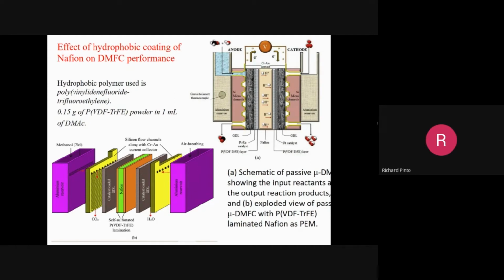The similar thing happens on the right side also. The only difference is the catalyst is only platinum, not platinum-ruthenium, because here H plus has to combine with oxygen, air-breathing oxygen, to produce water. This is the water symbol. This is carbon dioxide. So this is the current flowing in the external circuit, as I mentioned with the cross-strip geometry earlier. Electrons move in the external circuit, go into the cathode side and then combine with H plus and oxygen. So the current is drawn in the external circuit.